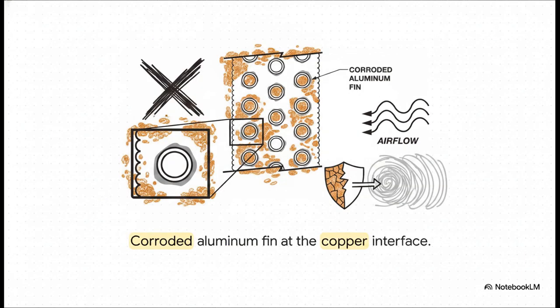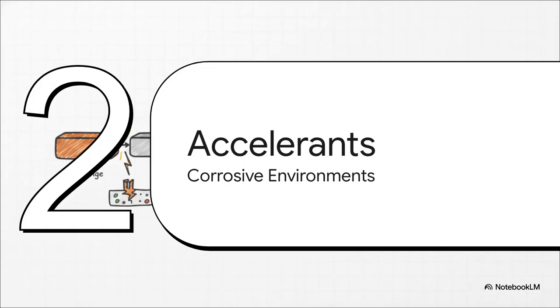And this brilliantly, or maybe tragically, illustrates the aftermath. Just look at the interface right where the copper and aluminum meet. The aluminum fin basically acts as a sacrificial anode and actually corrodes right at the contact point. And not only does this physical destruction completely ruin the thermal conductivity between the tube and the fin, but it also creates these nasty aluminum oxide deposits that build up and block the airflow completely. The system literally suffocates itself. So you might be wondering, where do these electrolytes even come from?